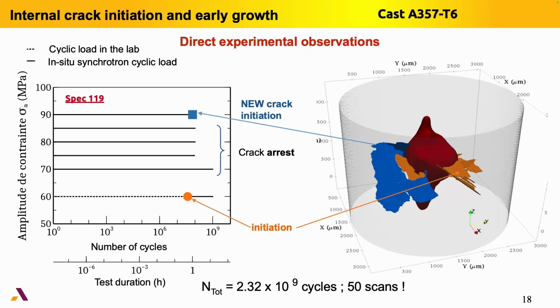So the first crack initiated is here, in orange. Here, in fact, there were 2 cracks, one here and one here, but these 2 cracks were arrested. And finally, a new crack has initiated after all this loaded history, but here on the back and here around. And these 2 cracks here are not connected. So in fact, we have the global loaded history of this specimen. And this history shows that in gigacycle fatigue, the crack initiation is not always dominating. So it is an important result. Sometimes the cracks are arrested.